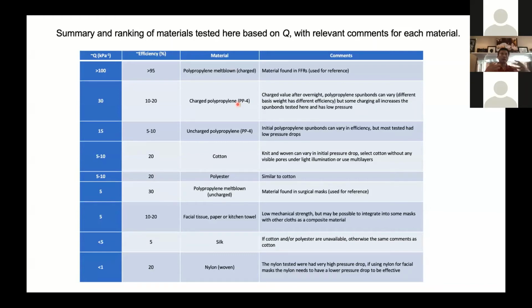And if you can identify these polypropylene materials, you do the triboelectric static charge. This is really good. Quality factor goes up to 30. If you don't do the static charge, uncharged, quality factor goes up to 15. Very good ones in these materials. If you have multiple layers stacked together, efficiency is very high, air breathability is very good.